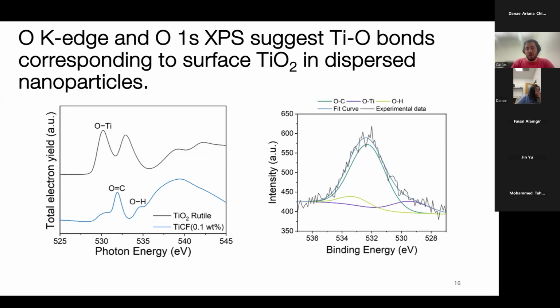And when we do XPS on this oxygen, we fit the Ti-O bonds, and we can also estimate how much of this titanium we have, which I think both of the titanium combined ends up being about 0.5 to 0.6 atomic percent in the nanoparticles.